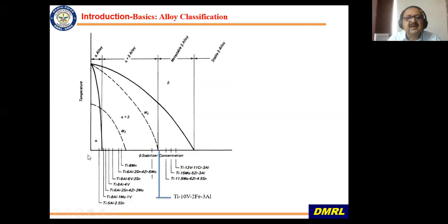Here again, the examples of certain alloys are given. From here in the alpha alloy category, you can see Ti-5Al-2.5Sn. You only have alpha stabilizers, and then commercial purity titanium also comes into this. As you all know, commercial pure titanium has got quite a good strength level, and it can compete with many of the aluminum alloys. That is why it's also an important category. And then you come into the alpha plus beta alloys, where one of the important alloys is Ti-6Al-4V, and 50% of the world titanium production is of this alloy.